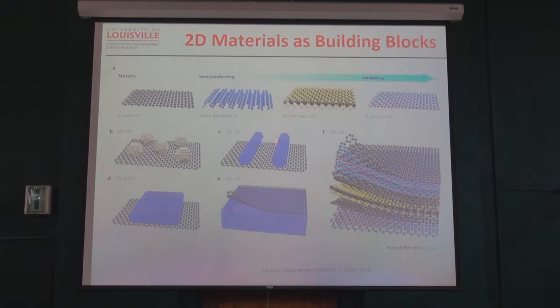Then I can draw nanowires or carbon nanotubes, and that is more like a 2D, 1D structure. Then you can have even 2D to 1.5. This is fractal dimension. In fractals you usually call it a 0.5, 1.5 kind of dimension. Then you can have 3D, 2D, like if I draw something on the semiconductor. Also with 2D materials, any of these materials you can draw one on the other. So if you go graphene on this WS2, then boron nitride, I can make a series of 2D heterostructures. Yes, a sandwich structure.